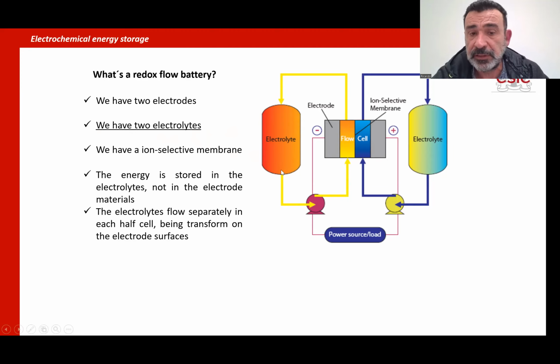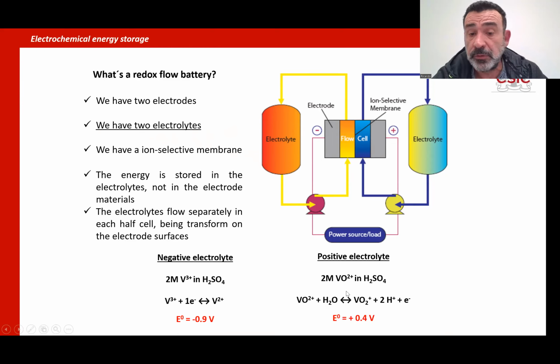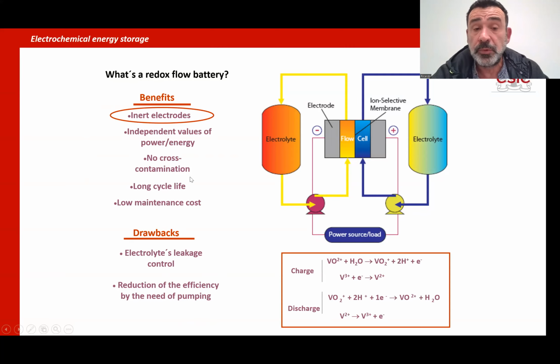Then in these tanks, you have the electrolytes, and they are pumped to flow within the cell separately, the positive and negative electrolytes. You have chemical reactions involved. For example, you have the reactions here with vanadium salts. In the negative electrolyte, you use this reaction, vanadium 3, vanadium 2, oxidizing and reducing. In the positive electrolyte, you have vanadium 4, vanadium 5, oxidizing and reducing. Okay, two different systems with their potentials, etc. What's the good point of this battery, the benefits? The electrodes are inert.